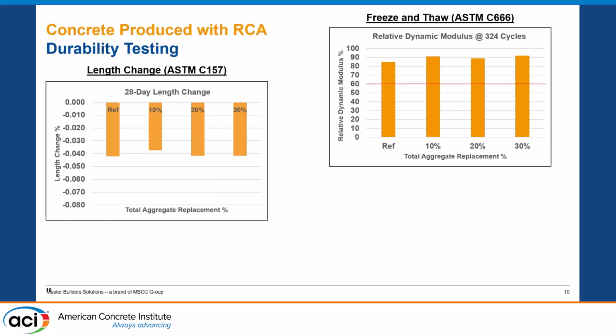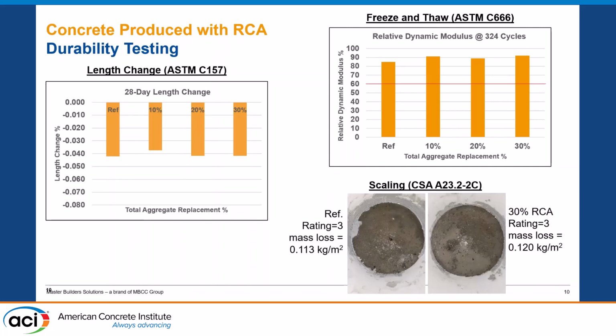Also very important, especially in the colder climates, is scaling. Here we used the Canadian test method, which evaluates not only the surface appearance of the concrete after going through 50 cycles of freezing and thawing with de-icing salts, but it also measures mass loss. And the ratings, so the visual rating of the concrete, the aspect of the concrete is the same, and the mass loss also very comparable.